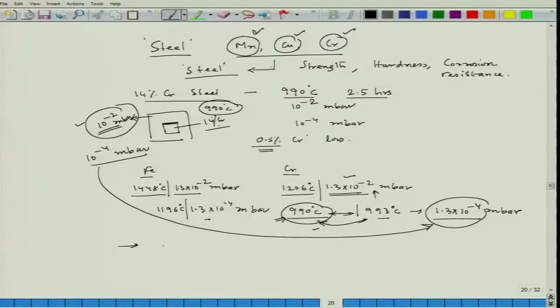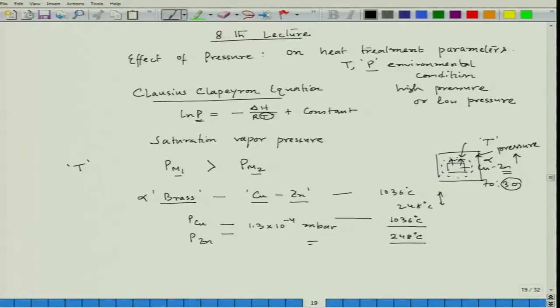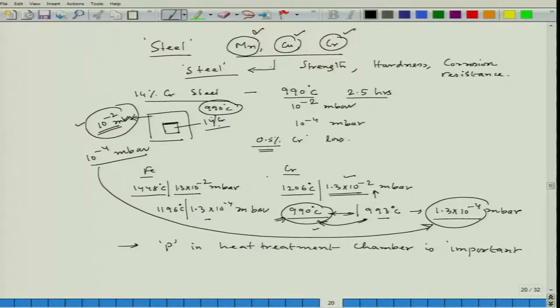We see that the pressure in the heat treatment chamber is critically important. In the case of zinc in brass, temperature is also a key factor. Even for chromium loss in steel, the chosen temperature must be carefully balanced — not too low to slow kinetics — while the chamber pressure must be higher than the saturation vapor pressure of the at-risk element at that temperature.